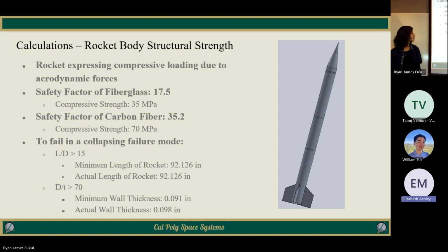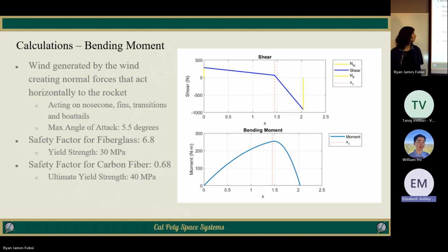And then in terms of why we can't use this carbon fiber, this is for an ideal situation if the rocket was flying straight up. The other situation accounts for the bending, which would be from the wind. And most likely there will be wind. The wind that this is calculated at generates an angle of attack for the rocket of 5.5 degrees. The average would be around 3.5, which still has a low safety factor, and it's using a different mechanical property of the carbon fiber than the other calculation is. Does that make sense? Yep.